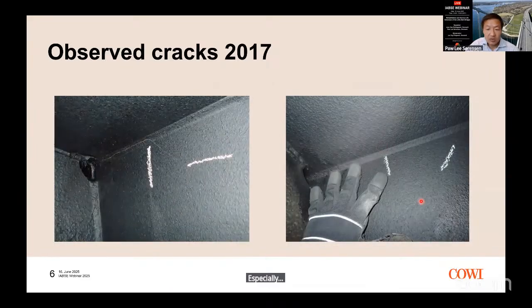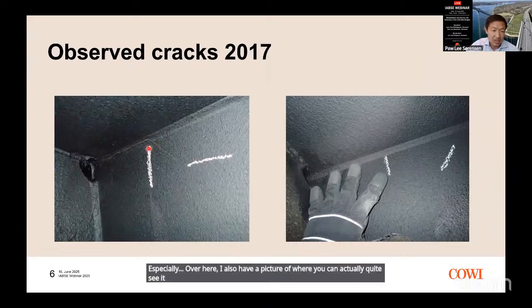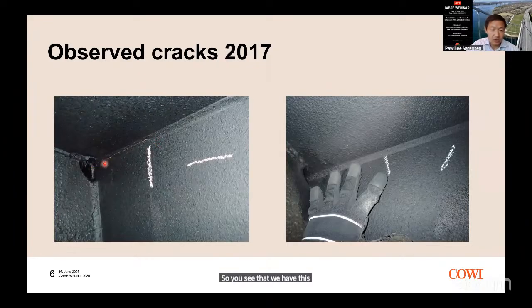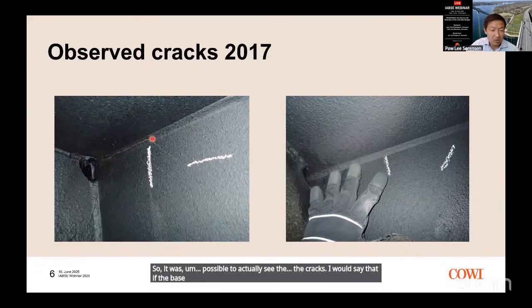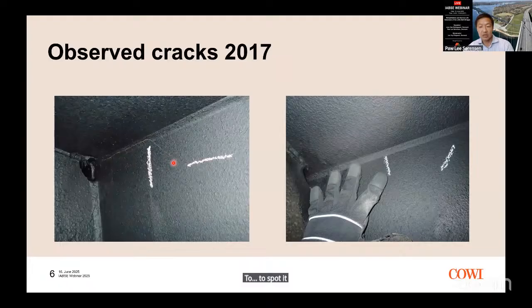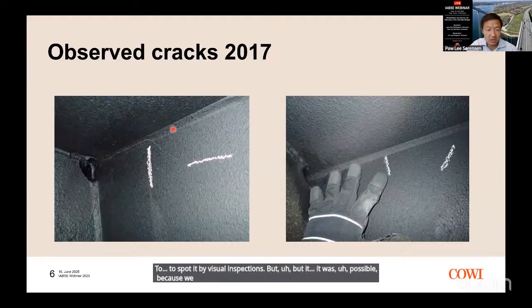Here I also have a picture where you can see it a bit more in detail. So you see that we have this orange base layer and the black top coat. So it was possible to actually see the cracks. I would say that if the base layer had not been orange, it would have maybe been more difficult to spot it by visual inspections. But it was possible because we had this combination of paint colors.